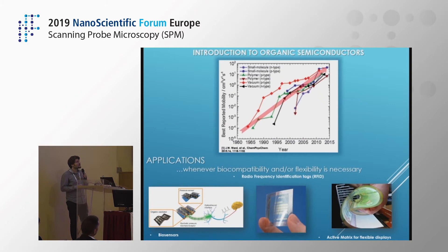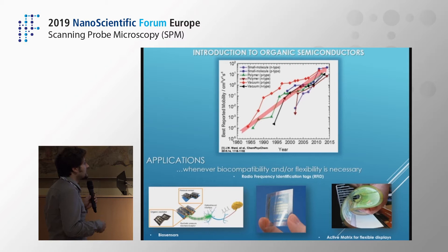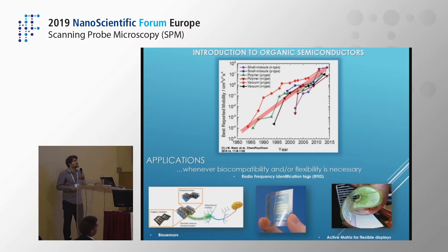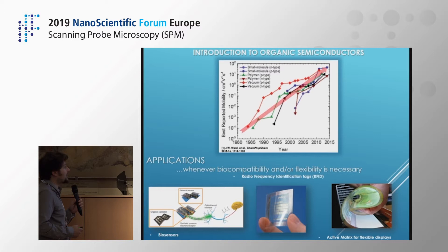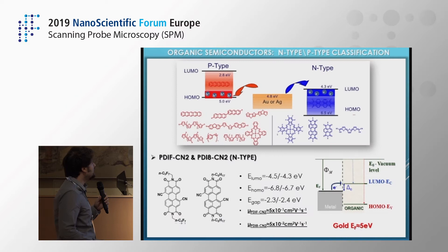Just a brief recap about organic semiconductors and organic transistors — those are of course polymers or small molecules. There has been a huge effort in the last 30 years especially in terms of the charge carrier mobility. Field effect mobilities now range in about 10⁻¹ to 10¹ cm² V⁻¹ s⁻¹, so we are quite far from inorganic standards like silicon. Despite this, there is a huge landscape of application for organic transistors, typically whenever biocompatibility and/or flexibility is needed.